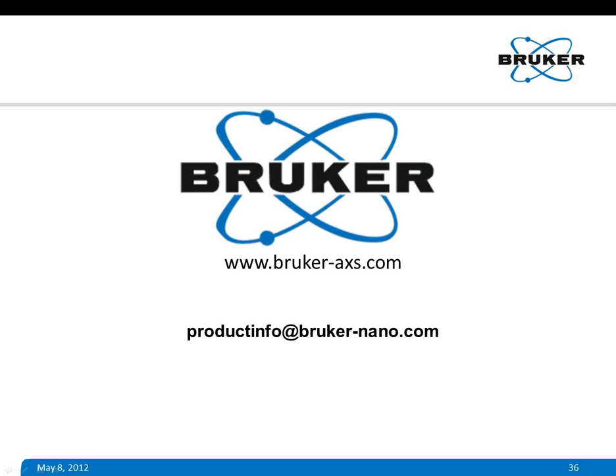Okay, there are several questions coming in. The next question has to do with epoxy coating systems. So can we use this test to evaluate epoxy coating systems and evaluate the effectiveness of a formulation and extrapolate the life of a system, or the life of the epoxy? Yes, it could be done. This will be almost like a non-conducting coating on a conducting surface if it is applied on steel or some other metals and alloys. And epoxy coating, of course, can be evaluated using scratch test procedure. As I outlined, you need to use some kind of conducting tip, maybe a tungsten carbide microblade, and attach it with an electrical contact resistance measurement system in our CETR-UMT scratch tester, and perform a scratch test.